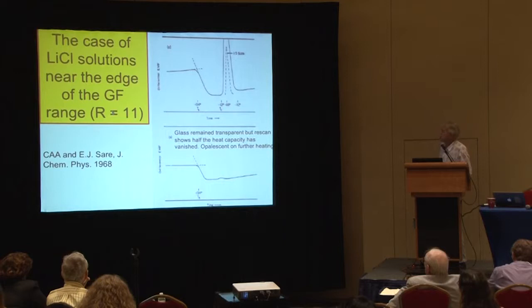So here's a paper which dates from quite a long time ago, dealing with lithium chloride water at the edge of its glass forming range, which is about 11 moles of water per mole of lithium. And you heat it up in this DSC, in the DTA was all we had at this time, and you see the glass temperature, and then a short time later, you see a huge inflection of your sample pen as a lot of heat is released. And you look at your sample, but it doesn't look any different at all. Except you don't want to look too closely because it's going to blow up in your face. It's going to burst the glass tube. And if you're lucky enough that it doesn't burst the glass tube, a little while later, you see it go blue opalescent, and then it turns white.